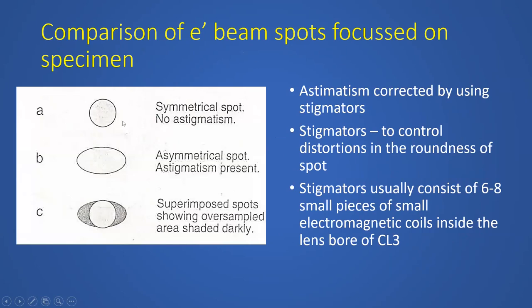Okay, so comparison of electron beam spots focused on the specimen. This is the kind of spot that you would like to have. It's a symmetrical spot. There is no astigmatism. Astigmatism is an aberration that results from unequal magnetic fields. You can compensate this using stigmators, which are basically 6 to 8 small electromagnetic coils placed inside the bore of the condenser lens 3. This is called a stigmator. For obtaining a good image in an SEM, especially at very high magnifications and high resolutions, you need to correct for astigmatism. This is a very common aberration and common problem. Unless you use proper stigmation, you won't get a good image.